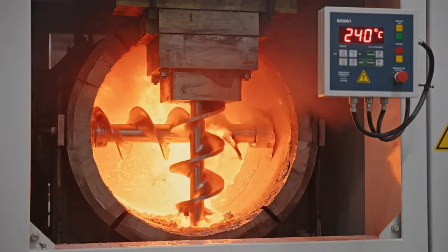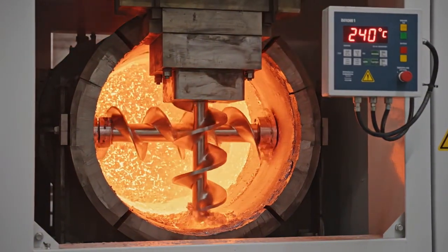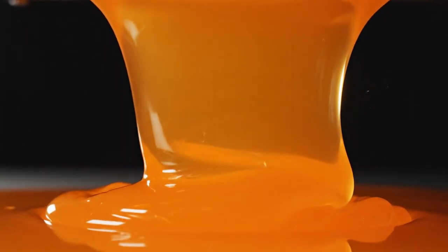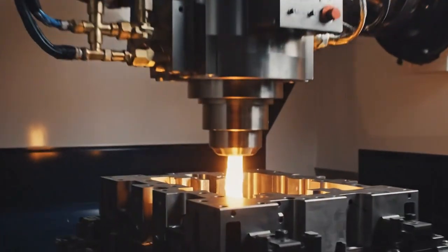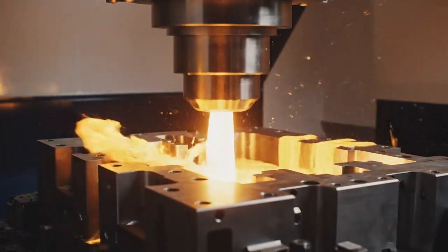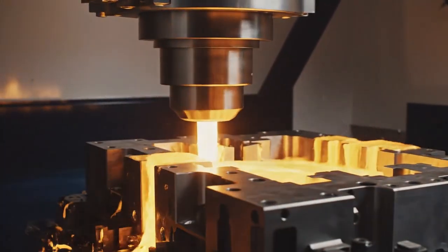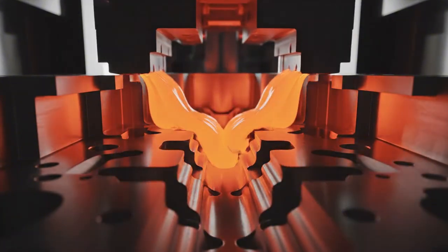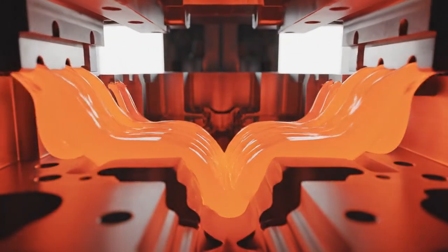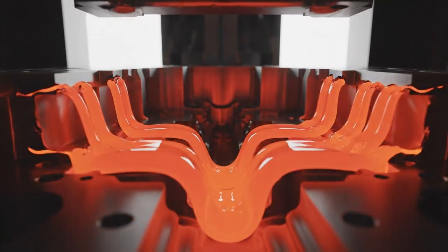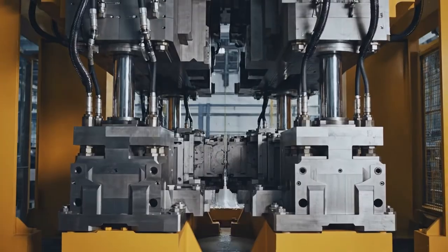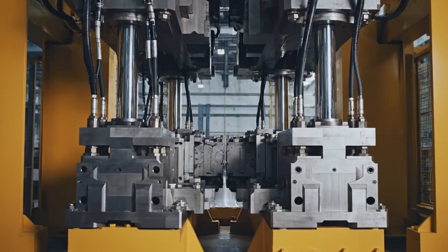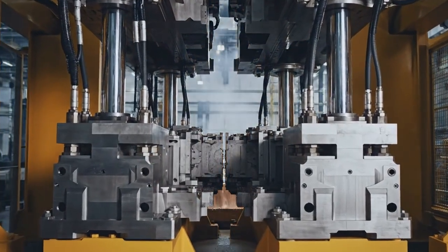Inside, a reciprocating screw simultaneously heats and compresses the plastic, raising its temperature to 240 degrees Celsius, the precise point where ABS flows like honey but has not yet begun to degrade. When the screw reaches its forward limit, the accumulated melt is injected into the mold cavity at pressures exceeding 1500 bar. The injection takes less than 2 seconds, but in that brief moment, molten plastic flows through the mold's intricate geometries, filling every corner, every undercut, every microscopic detail.